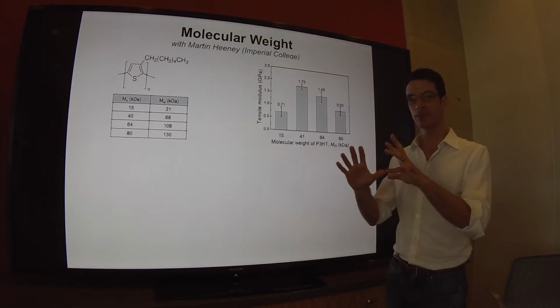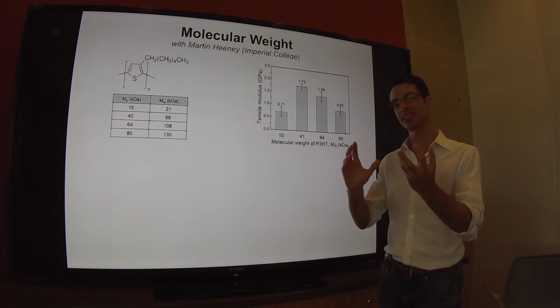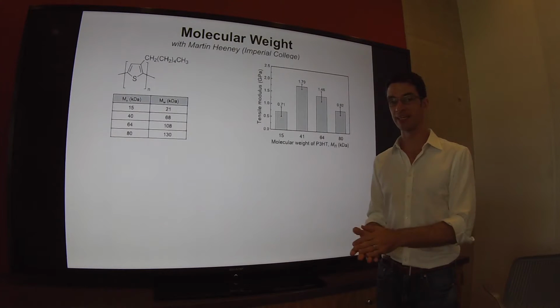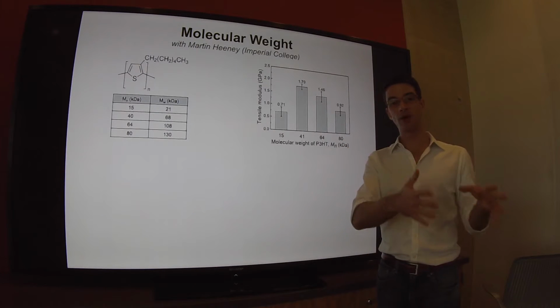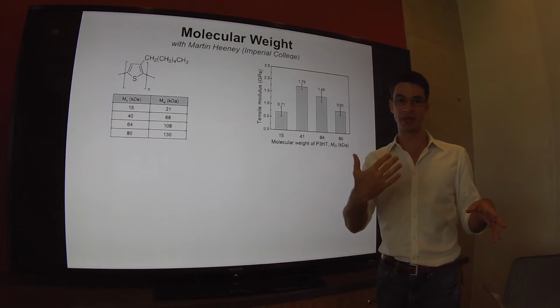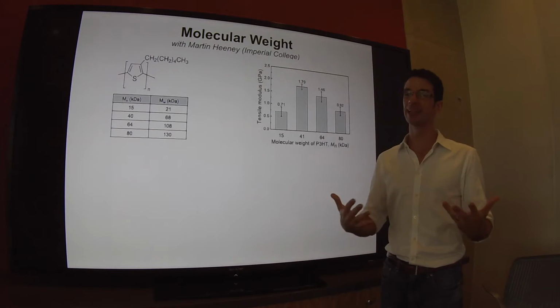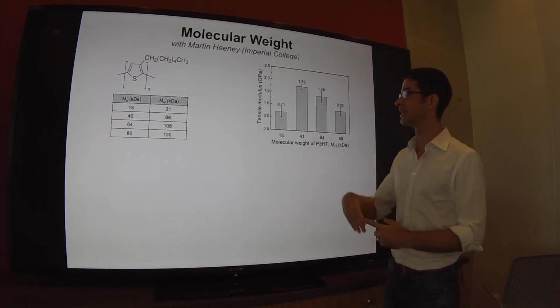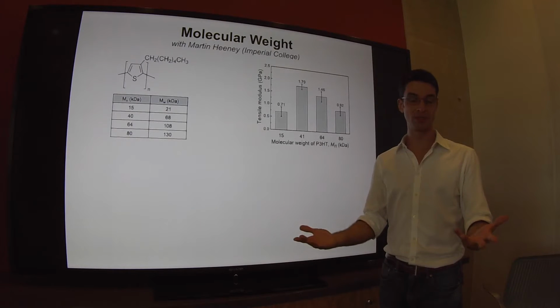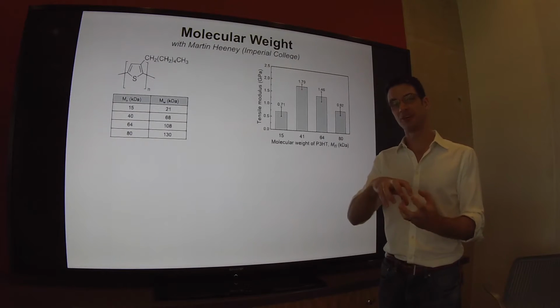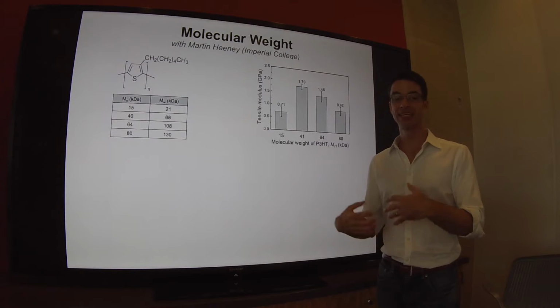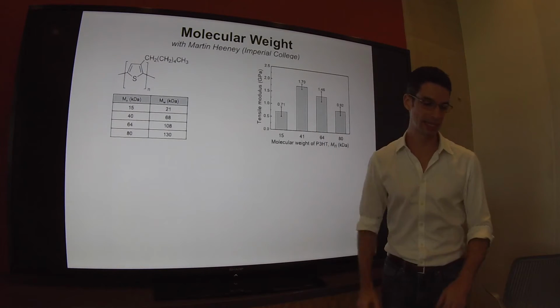We expect some kind of unusual behavior that is a manifestation of multiple effects, because at low molecular weight you might have a greater crystallinity depending on the material. This is just one effect, which could increase the modulus, but then you have fewer entanglements. So it's not a simple relationship.